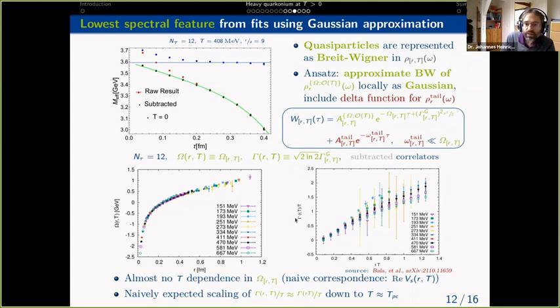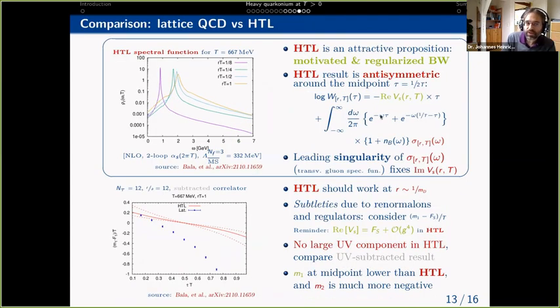If you look at the width, we have used a Gaussian here, so we have to rescale this width in order to make it comparable to the width of the Breit-Wigner. And you see that the width, after dividing by temperature, as a function of rT shows totally trivial naive scaling. So in these units, there is practically no temperature dependence left anymore. Now, this Gaussian approximation certainly is an assumption. We could also use something else.